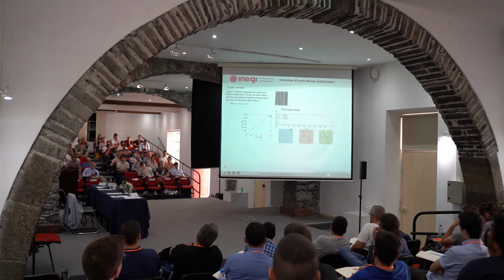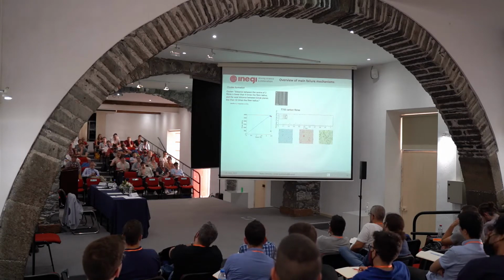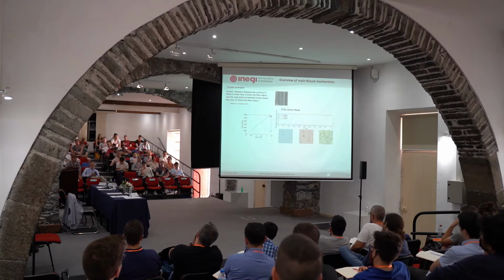So this is the process, so you can see that you don't have a macro crack that then breaks your specimen. You have fibers that break in different locations, you have a process of cluster formation, and then everything falls apart, okay? And again, from computational micromechanics, we can capture that.